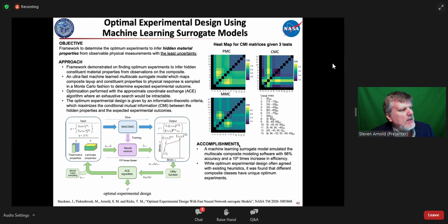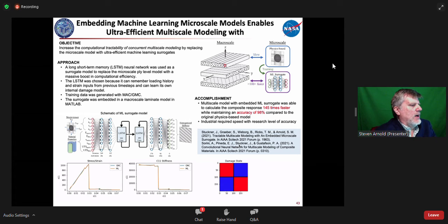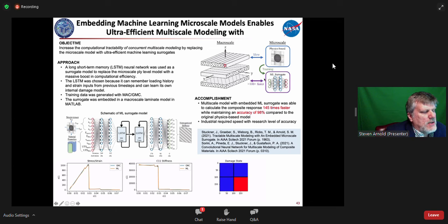But after doing this, we decided, let's model the ply instead of the entire multiscale. And obviously instead of just 5 points, we wanted to map the entire stress-strain curve. So Josh went off and developed a long short-term memory neural network model to represent MAC results. And again, after training, we were able to show that once again we could accurately predict the response that corresponded to what we got from MAC, but at 145 times faster speed. So that's 2 orders of magnitude increase, where we embedded this surrogate model into a MATLAB lamination formulation. Again, this is very encouraging and very promising.